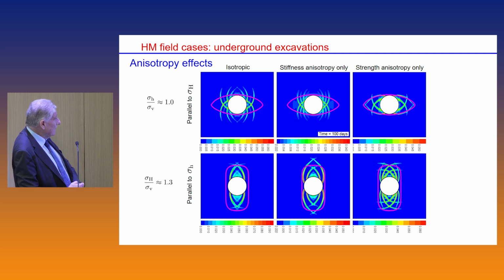For instance, if we take excavation parallel to the major principal stress, so we have this isotropic stress state. Obviously, if you use an isotropic model, we'll not get this anisotropic EDZ. If you only introduce the stiffness anisotropy, you don't get the right result either. You only get the right result when the strength anisotropy, which is the key factor here, is introduced. In the perpendicular direction, you can see in the three hypotheses, the configuration of the EDZ is not that different. It seems that in this particular case, the initial stress state is the dominant factor